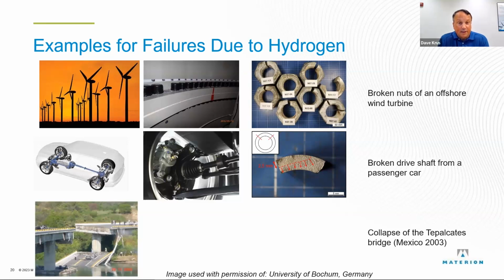The drive shaft in a car, same thing, cracked. And talk about a slow, long time crack that did some really bad damage: that bridge in Mexico that fell. They definitely chose the wrong steel for that one in a corrosive environment. The failures could be catastrophic. They usually are. What happens over time is, as you pull the metal, you create some more defects. The hydrogen tends to rush to those defect areas and make them more brittle, which then slowly accelerates it and makes the cracks grow right where they are.